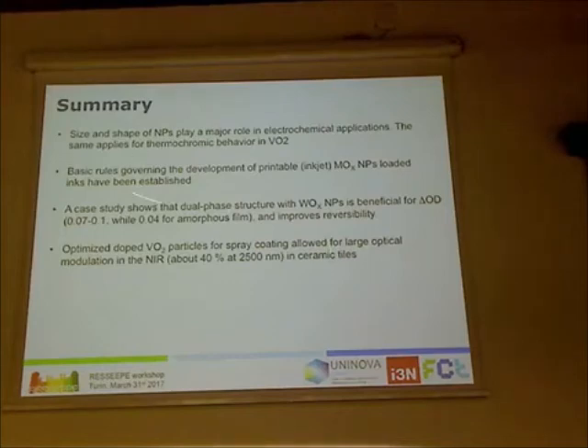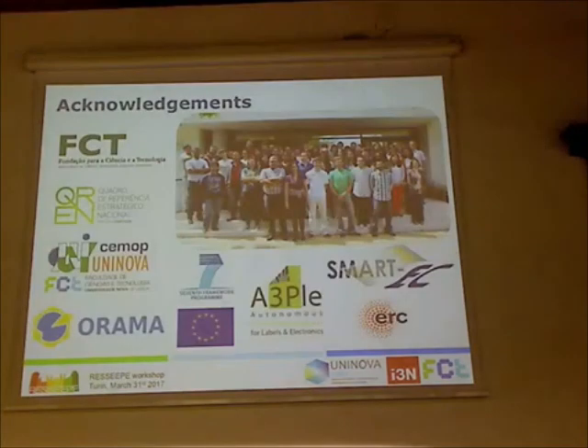To finalize, size and shape of nanoparticles can control their role in electrochemical applications. In this case, I've shown improvement of the electrochromic properties through proper design of particle size and shape. We could print this using inkjet techniques, creating electrochromic foils with improved properties using the dual phase layer, and we also optimized VO2 particles that can be spray coated onto tiles, achieving about 40% near infrared modulation in ceramic tiles that can be used on building roofs. These are some of the projects that financed this research, and I want to thank you for the opportunity to present and talk about these results.